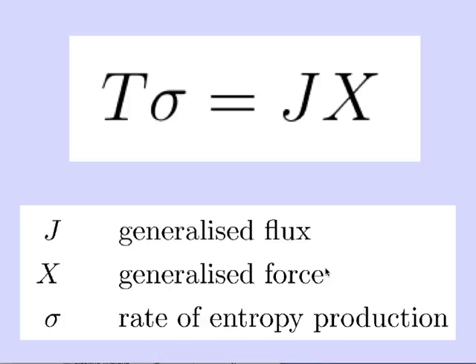So imagine that we have a flux J, right? And this is a generalized flux. Flux means the rate of flow of something. And we have a force X which is driving that flux, right? So that could be a free energy gradient, could be a temperature gradient driving heat flow, etc. Then the rate at which energy is dissipated is the temperature times the entropy production rate. So sigma here is the entropy production rate. If I multiply entropy by temperature, I get an energy. So if I multiply the entropy production rate by temperature, I get the free energy dissipation rate. Okay? So this equation tells you that the energy dissipation rate will be the product of the flux J and the force X.